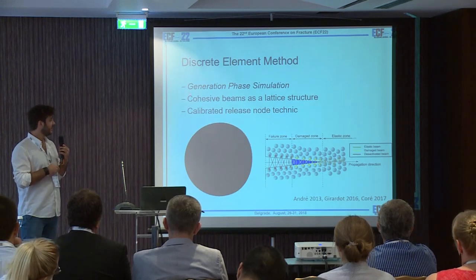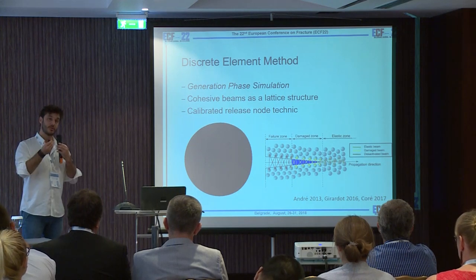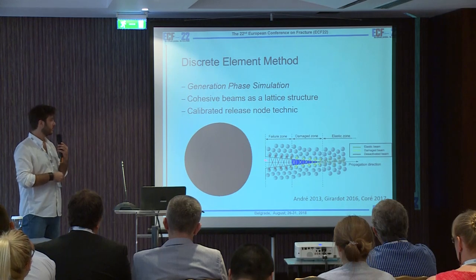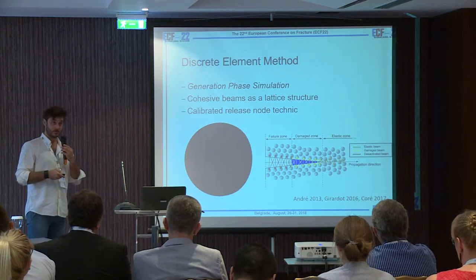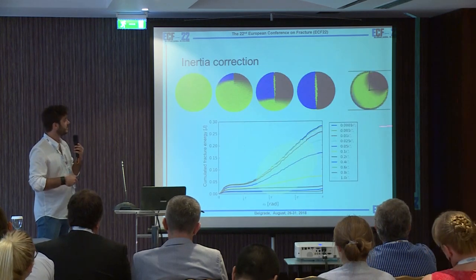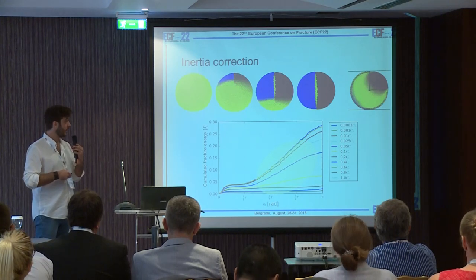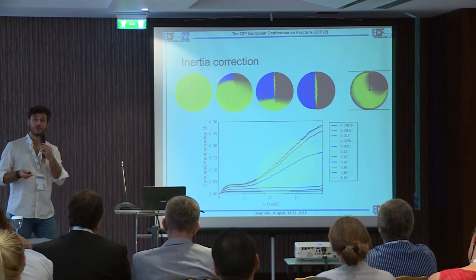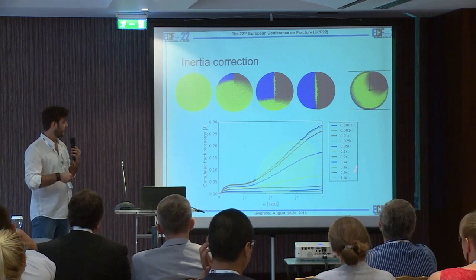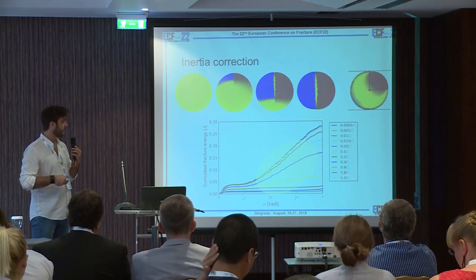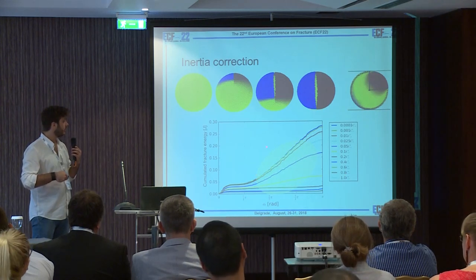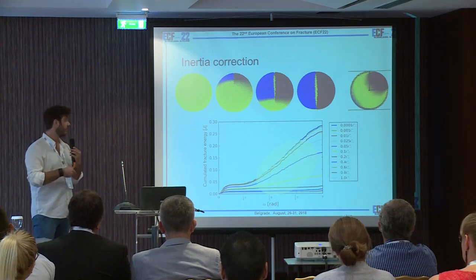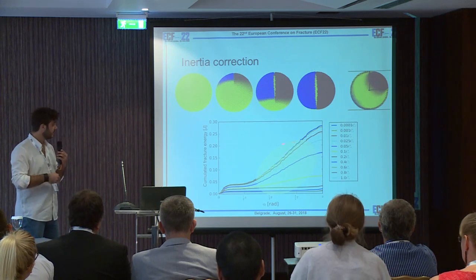Be careful: this simulation is a generation phase simulation, so we do not have fracture criteria. It is the user that opens artificially the cracks, because the aim of this simulation is to perform an energy balance. As you can see here with the displacement field, we open artificially a crack from the top to the bottom at a certain crack velocity. Then we can obtain the cumulative fracture energy thanks to an energy balance of such a simulation. This graphic gives the results for different crack velocities, and we can see that at a certain moment of the propagation, a quasi-stable state is reached.